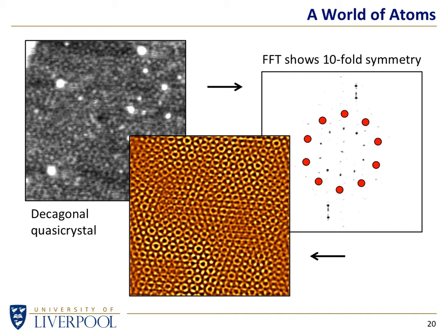It's almost to the point of suspicion where you think, how on earth can you get anything so clear out of anything that's so grubby? Well, you've got to be careful that you're not over-processing the image, and you've got to be careful you're not fooling yourself into thinking that things are real. But as a check, for instance, we can look at a little rosette of atoms that form this tenfold ring here, and if we look back to the original image, it's rather more fuzzy, but I hope you can see from where you're sitting that there is actually a tenfold little flower there, just like there is there.